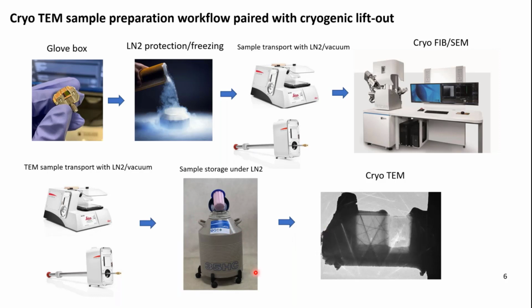So let's say we have a TEM sample here under liquid nitrogen. It is always inside a cryogenic grid box, which the majority of cryobiologists use. So I borrowed the concept from the cryobiologists. The sample is in a cryogrid box, and you can transfer the cryogrid box to the system where we can put the cryo box for the cryo TEM holder. If you purchase a cryo transfer TEM holder, there's another working station for the box for the TEM holder where we can handle our half grids, and where we can put our samples to the TEM grid groove. So the answer is we have to use a cryo transfer holder for doing that.